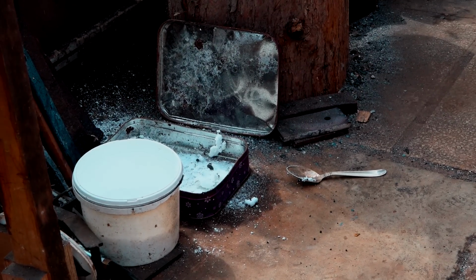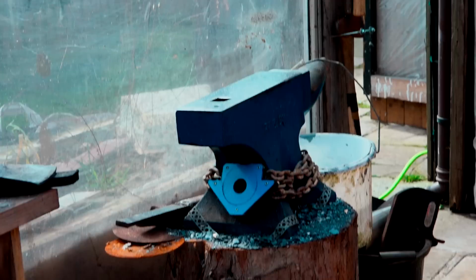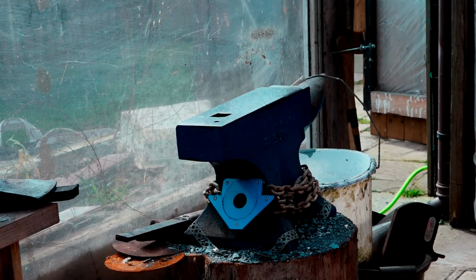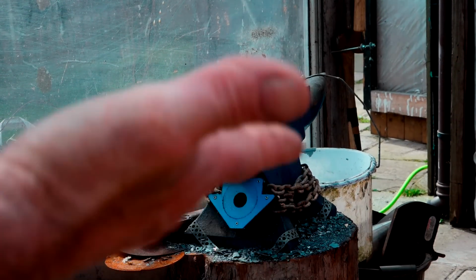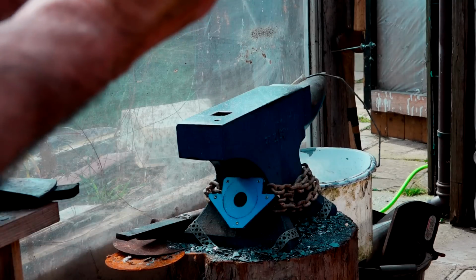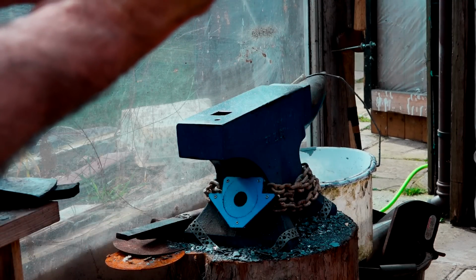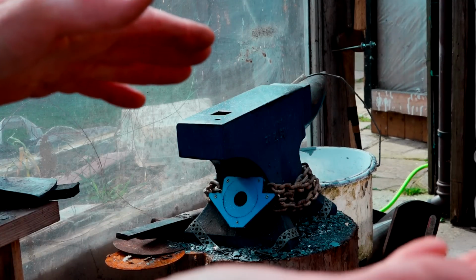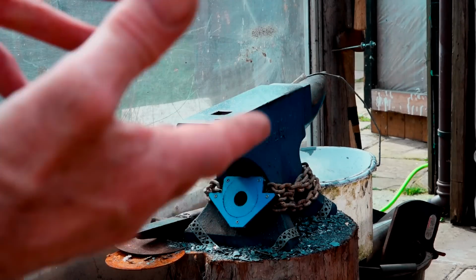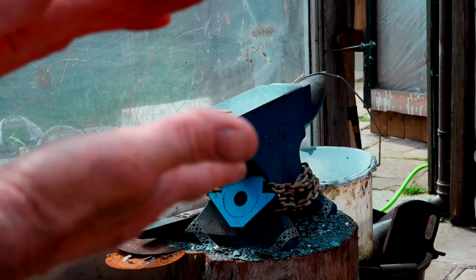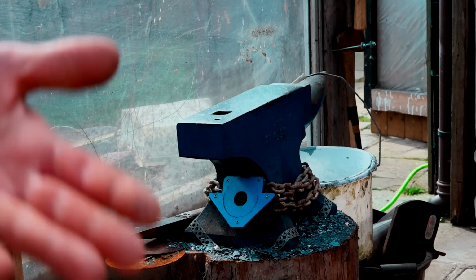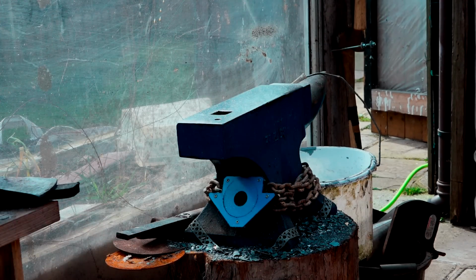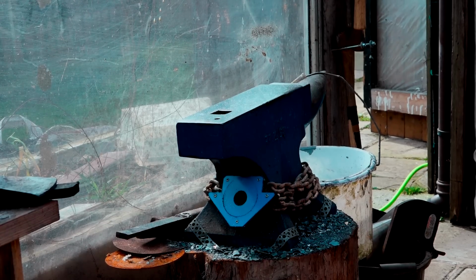Down on the anvil, and you hear a sort of crack from the steel, and it is a proper real crack. When that happens, you know those two surfaces have mated together. It literally forces the borax out of that surface. So every now and then when you hit it, especially when you first put steel together, if you're only using thin layers, you'll just get a crack. That's your steel binding together. That's a good sound. We like that sound.